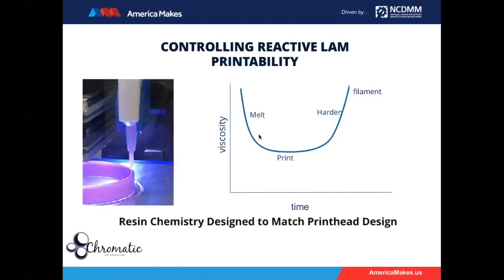And just a little bit more about how we control that printability, it's really not that different from what you see with a filament. If you think about the filament, when the material melts, the viscosity drops. You have a printing processing window of viscosity where that printing is happening. And then as it cools, it hardens to form the shape. This is basically what's happening in FDM. And we know that we can adjust the performance of that printing of the resin by adjusting the temperature at which the print head is at, and we can also adjust the temperature of the print bed. And this combination of dials allows us to alter the performance and quality of our print.